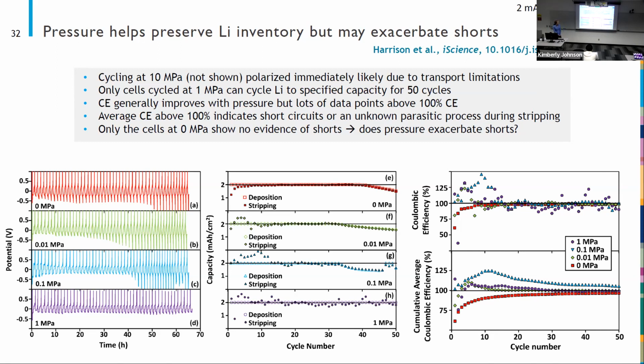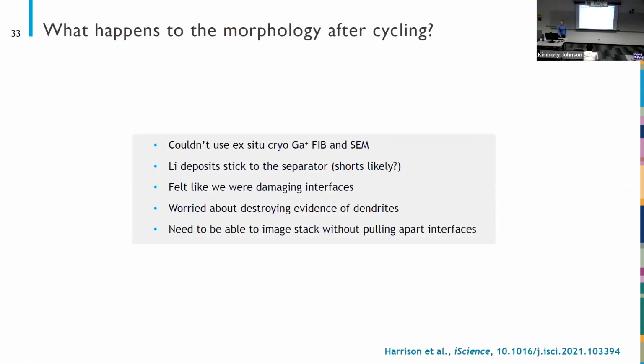But what we did to understand that better is to look at the cumulative average of the coulombic efficiency, and that's shown in the bottom right. And you can see that even if we average the coulombic efficiency, we're over 100% in all the cases except at 1 megapascal or at 0 megapascal. So only our cell that's under no pressure is performing without what we would suspect are short circuits. So this begs the question of whether pressure is exacerbating dendrites rather than squashing those dendrites. That's our first clue that that's what's going on.